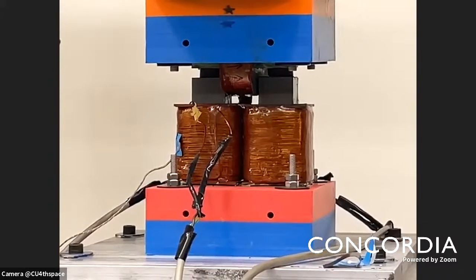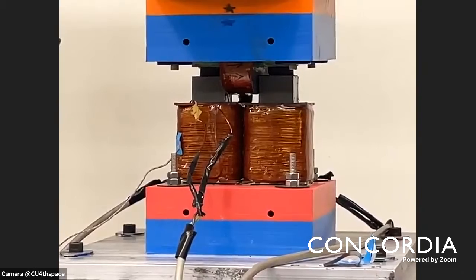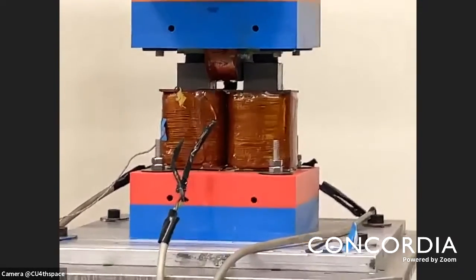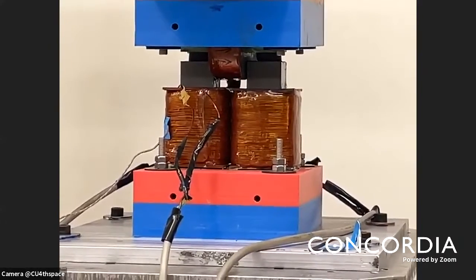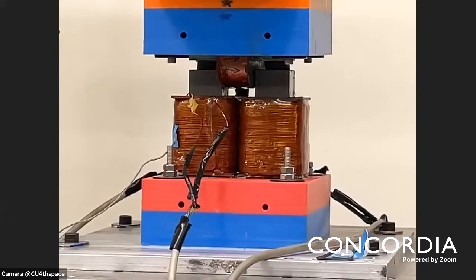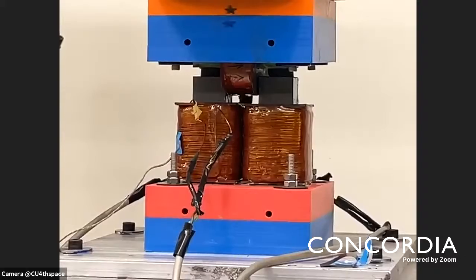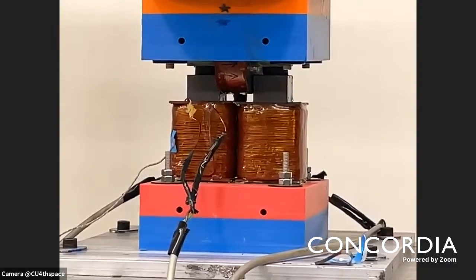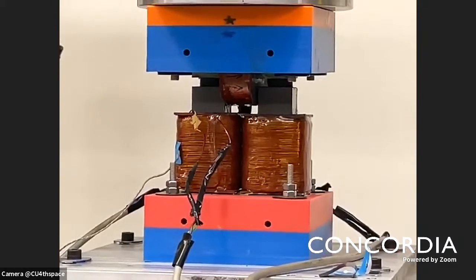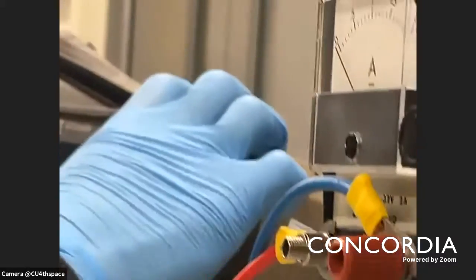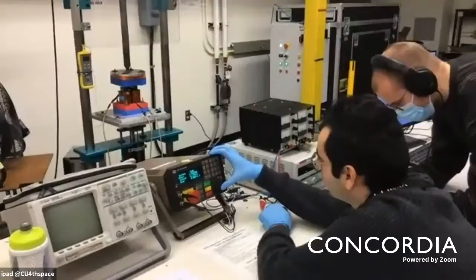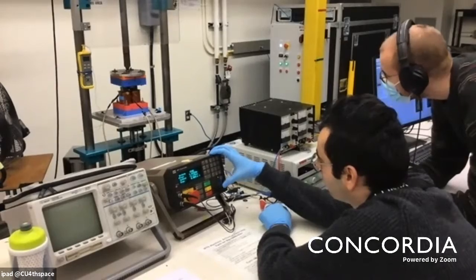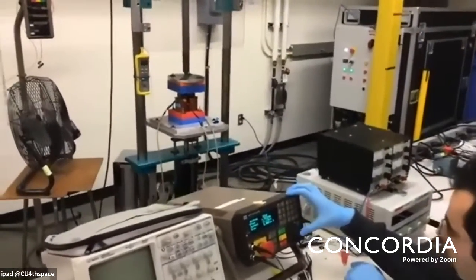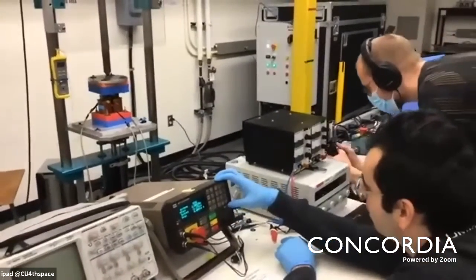I think, okay. So I'm going to apply the harmonic oscillation. As you could see, there is a movement. I can go up and increase the frequency a little bit. Around 1 hertz is the frequency of oscillation. Now I can put it at around 2 hertz. So a sinusoidal dynamic loading is being applied to the samples.